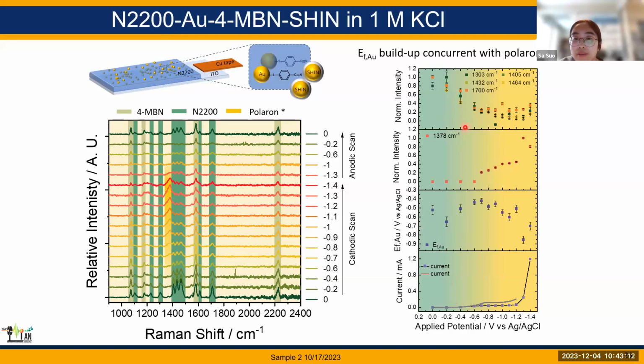So to the right is a summary of what we observed, basically. The top panel indicates the neutral N2200 Raman amplitude. After a certain point, it decreases. And the second panel is the polaron-related peak, the new feature upon doping. We can see that after -0.6, there is a growing intensity in this polaron-related peak. Concurrent with the appearance of the polaron peak, we saw the Fermi level of gold start to shift. And I believe this is our major finding till now. I will discuss this more specifically later.